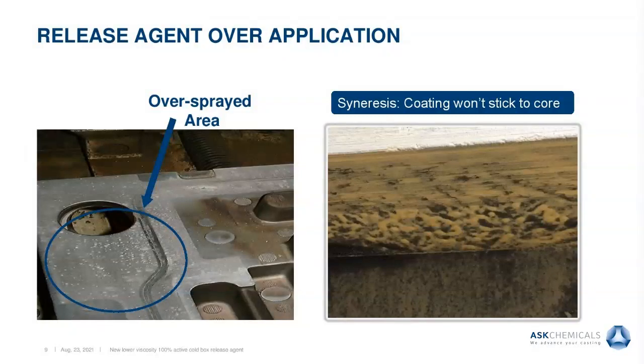The picture on the left shows an area where a release agent was oversprayed. Overapplication is typically the largest issue when it comes to release agents, especially those that are 100% active. Droplets of release lead to stickers. The picture on the right shows an area where there is too much release agent and a refractory coating was applied. The coating isn't sticking to the core or mold surface. The coating is pulling away, which is what we call syneresis.